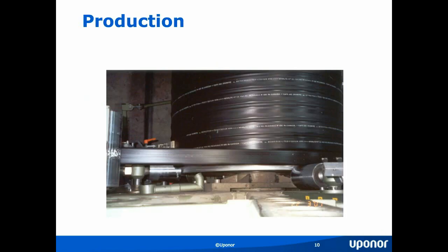So on this picture, as I mentioned, the pipe is made by first producing a profile, as you see on the bottom of the picture there, and we take that profile and we begin winding that around the drum. And as we're winding it, we're welding both the inside and the outside wall of the profile to create the helically wound pipe. And as I mentioned, the pipe diameters range anywhere from 18 inches up to 11 feet. And if it were shippable, we could even go larger, but we are restricted by transportation and their regulations.